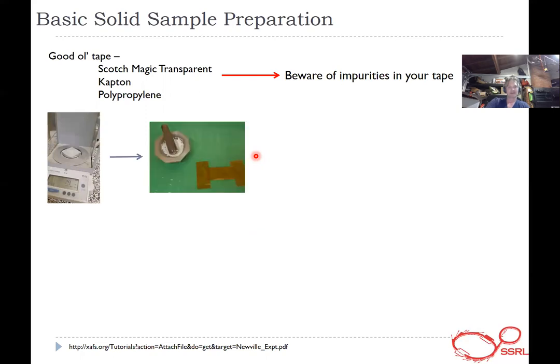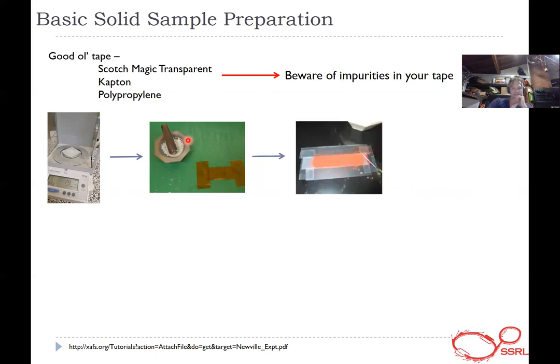So you're going to weigh it out and then you need to grind it. This grinding step can't really be overstated, how important this is. You need sample particle sizes smaller, if possible, than your absorption length. So grind, grind, grind. In a lot of cases, sieve, sieve, sieve. Don't leave this to chance if you don't have to. Put some Kapton tape down, tape it on both sides, and then you can lightly smear it across the tape.